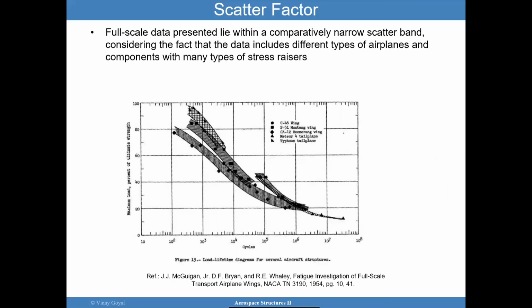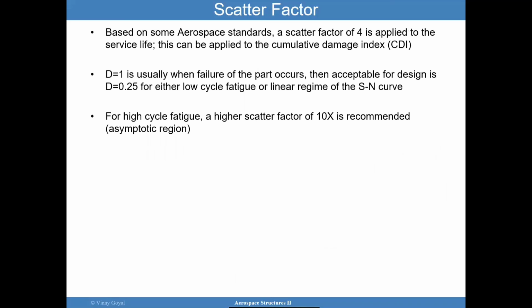Go to here, the scatter factors here. Based on some aerospace standards, a scatter factor of 4 is applied to the service life. So you can apply it directly to the cumulative damage index, which is one approach. A D of 1 is usually failure, and you can accept a damage of 0.25. So if you can keep the cumulative damage less than 0.25, you're in better shape.